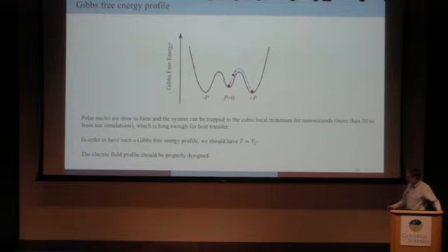And in order to have such a Gibbs free energy profile, we have temperature near the Curie temperature. Not below, but not quite, not too far away. And the electric field profile should be properly designed.